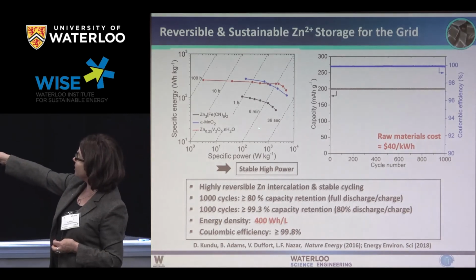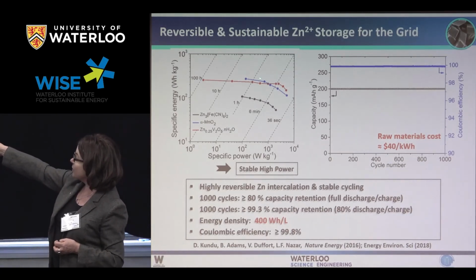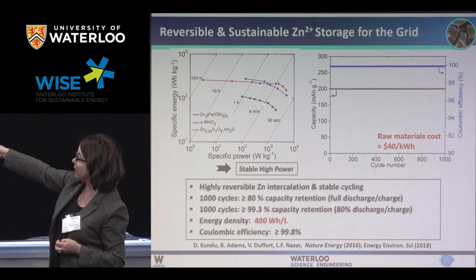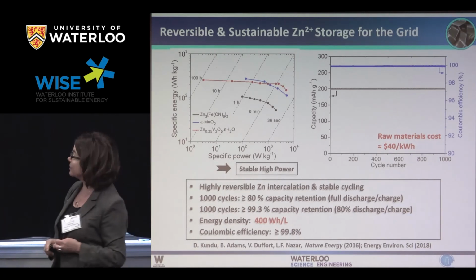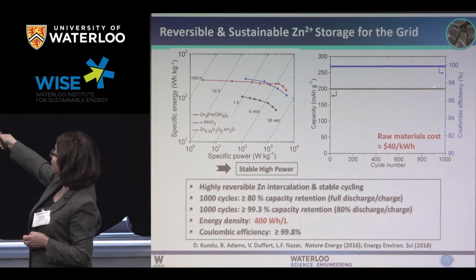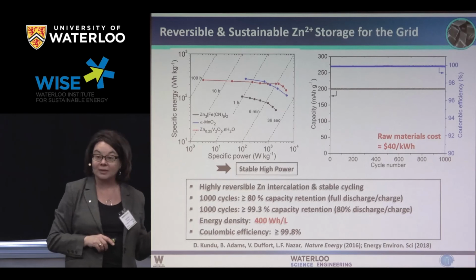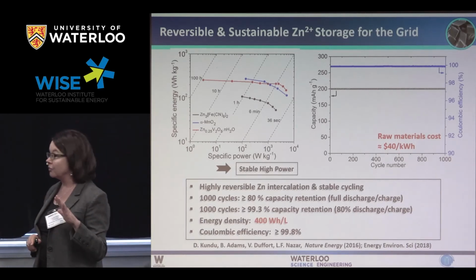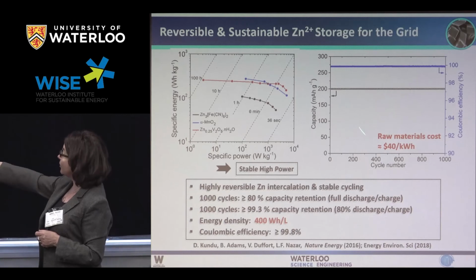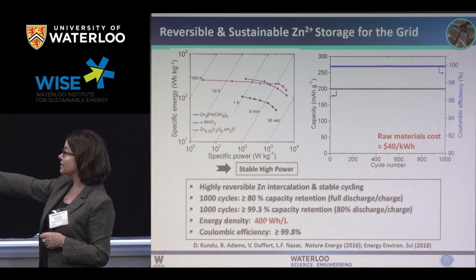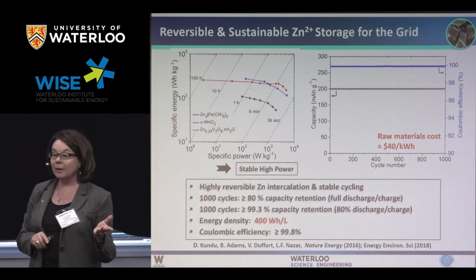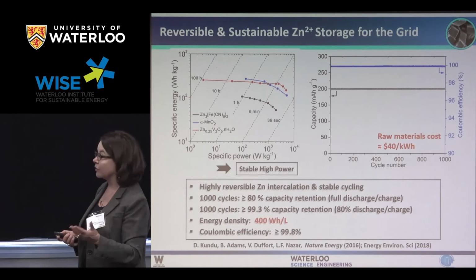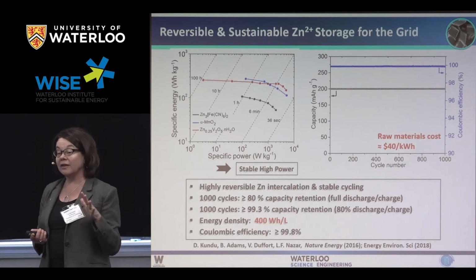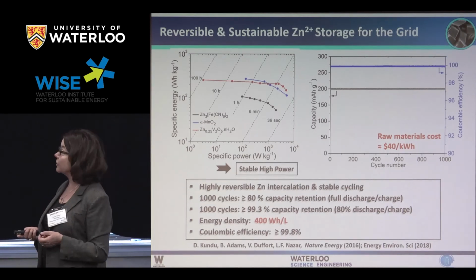And so when we compare our data, which is shown here in red, to the only other two zinc ion type cells that are available, and we're plotting energy versus power, you can see that they're very comparable to this manganese dioxide system, but they have even better power capabilities. And we can cycle these for 1,000 cycles with virtually no loss in capacity, as long as we don't go to full depth of discharge, at a fairly low materials cost, and at a fairly good energy density, which is about half that of a lithium-ion cell, but we're not using them for cars. We're aiming at this for grid storage. So this is, at least to my mind, a really good example of how nanomaterials make a huge difference.